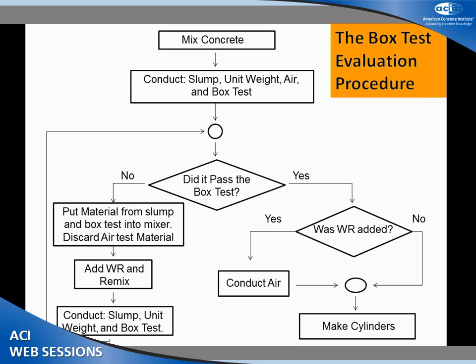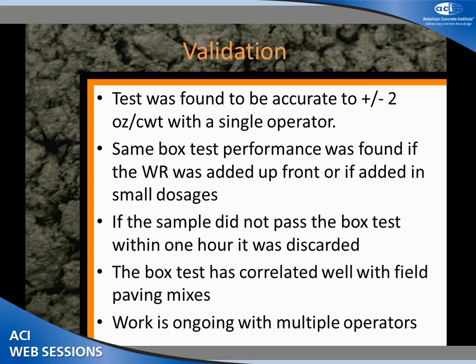After that, we run air, make cylinders, and we're done. The test is found to be accurate to plus or minus two ounces per hundred weight. The same box test performance was found whether we added water reducer in small dosages or all at once. If the sample did not pass the box test within an hour, we trashed it. The box test correlated well with actual field paving mixes, and work is ongoing to look at multiple operators.